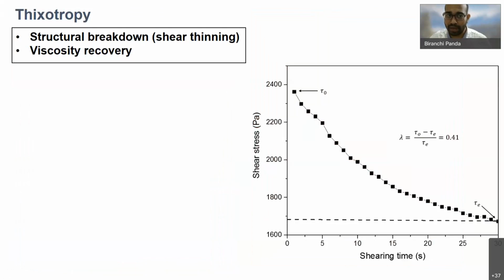Now, when you have thixotropy behavior in the material, it is very important to characterize the thixotropy. Otherwise, we cannot create a new mix design. So to characterize the thixotropy, we use a rheometer which was available in our lab. We did two tests: one is shear thinning testing, and the other is viscosity recovery, to measure the thixotropy of our material.